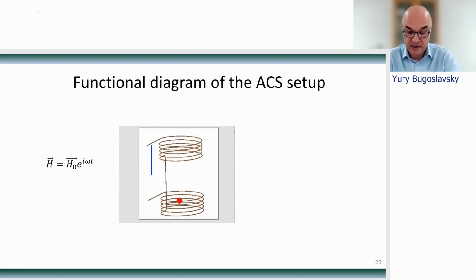When the sample is placed inside one of the coils, it takes the coil out of balance, and the resulting signal is proportional to the susceptibility of the sample. The balanced pair of coils is a very sensitive device and can therefore be used for measuring small samples.